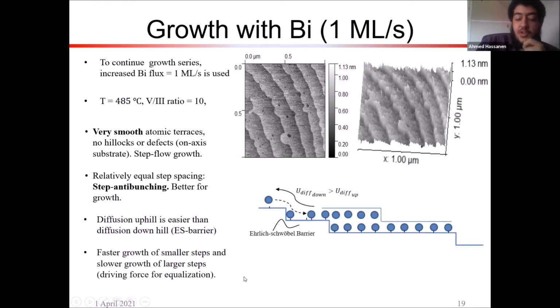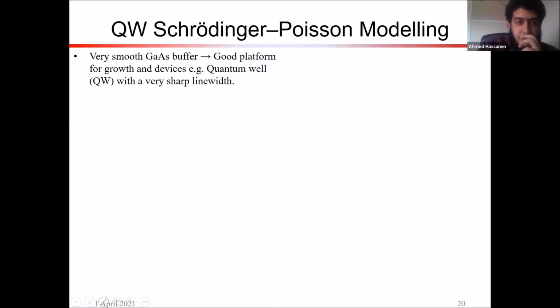And so what happens here is the Ehrlich-Schwoebel barrier is actually, when we use bismuth, helping us get the step anti-bunching, or these equal spacing of the steps, because the diffusion uphill is easier than the diffusion downhill. And so there's a faster growth of the small steps and the slow growth of the large steps. So there's this driving force for equalization of the surface. So that was a pretty interesting find.